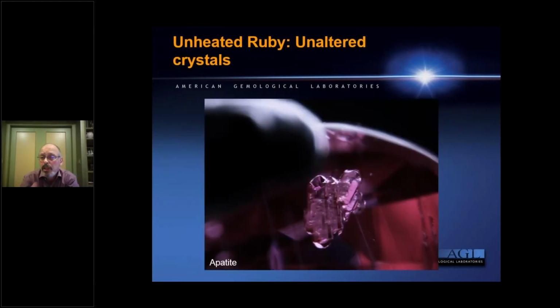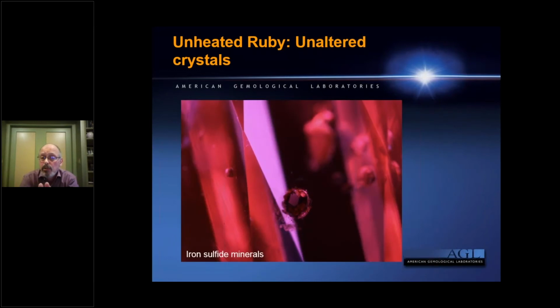You have other minerals like apatite. Apatite is a little bit more thermally resistant than calcite, but these also will tend to alter at relatively low temperatures. You have things like micas, you have things like iron sulfide minerals like you see here. So when you see these kinds of inclusions that show no signs of alteration, you have much more evidence that the stone is indeed unheated, or natural color.